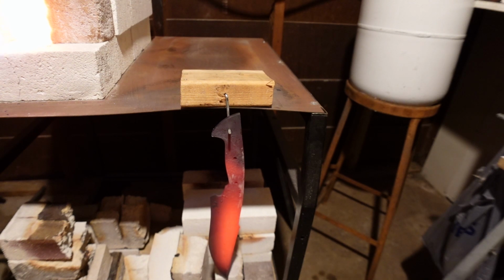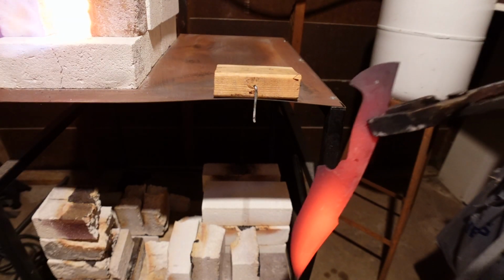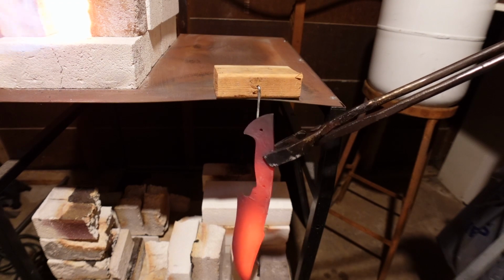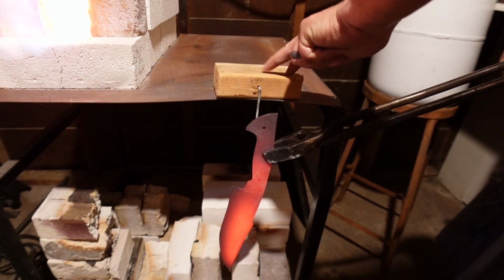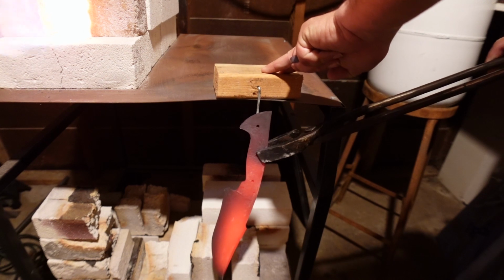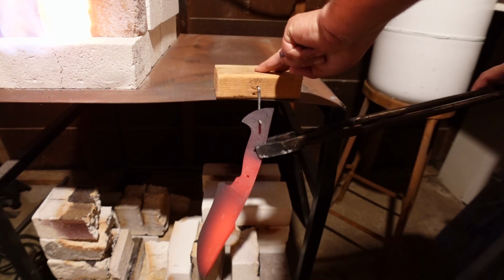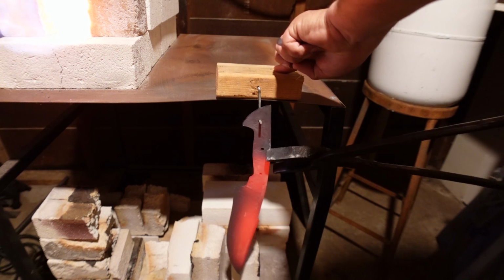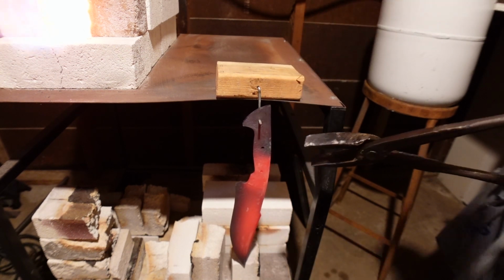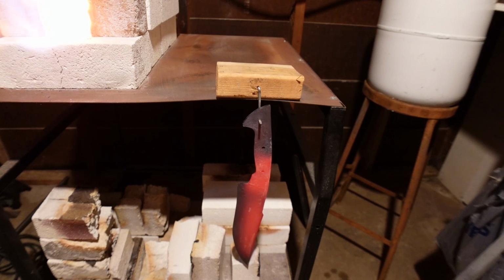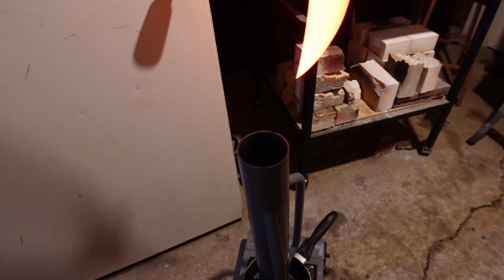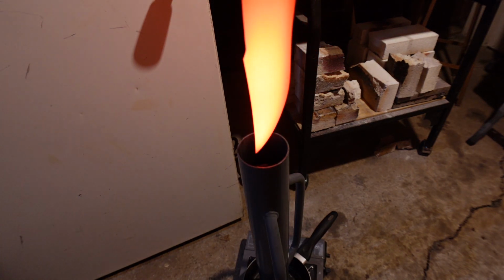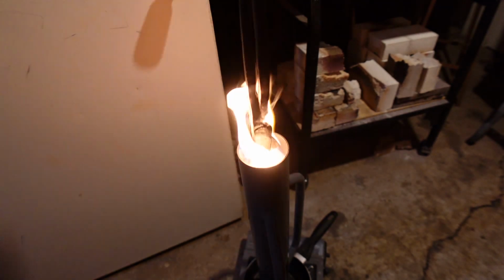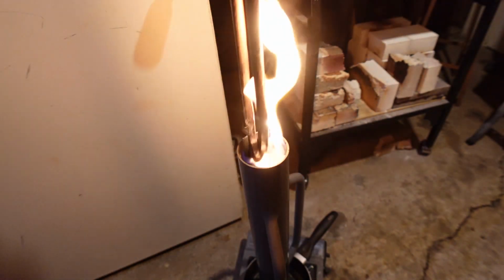So once we did that cycle, brought it up again to 1420 degrees, and then let it air cool. And once those normalizing cycles were done, we did end up bringing it back up to just under 1550 degrees. It was right at that 1550 mark, and then we quenched it in 120 degree peanut oil. And whenever you do this, you do want to agitate it so that it cools how it needs to and you get a nice even quench.